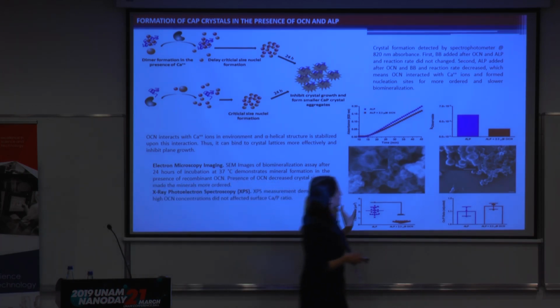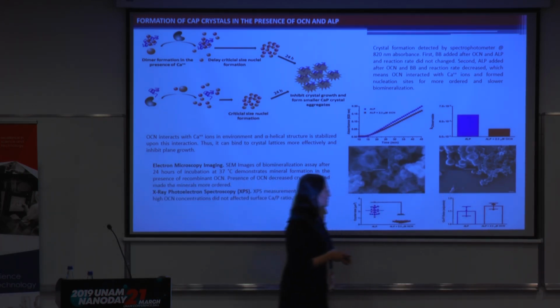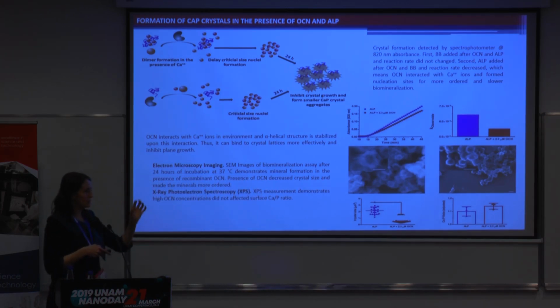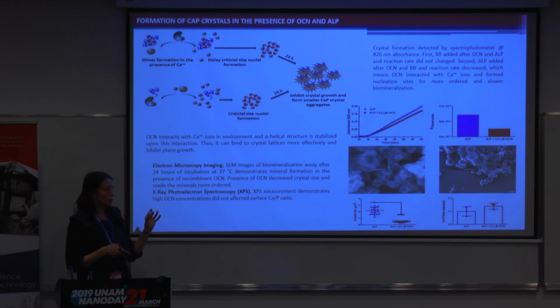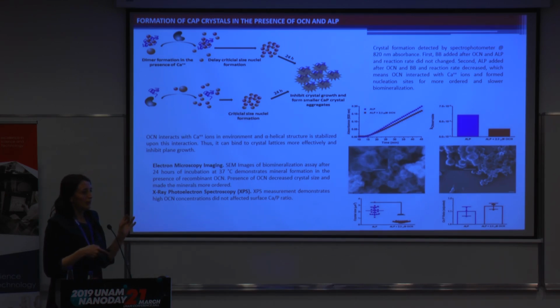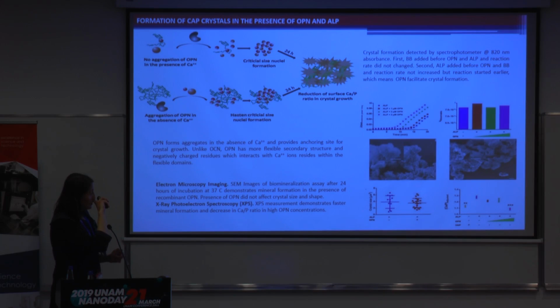As you can see, in the presence of osteocalcin, the size of the calcium phosphate crystals are smaller, which means that osteocalcin inhibits crystal growth, and we can control the size of the crystals, and we can prevent ectopic calcification by using osteocalcin, which means that we can produce our minerals as we wanted, and we can stop the mineralization in undesired conditions. And the other protein is osteopontin, and which we observed that.